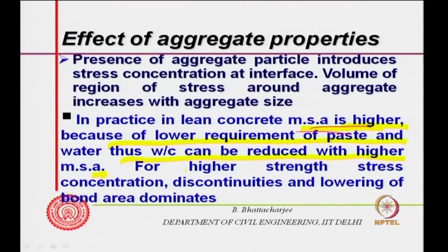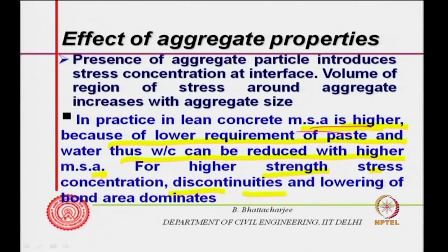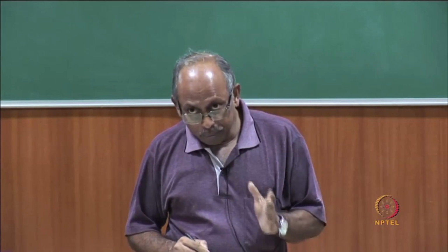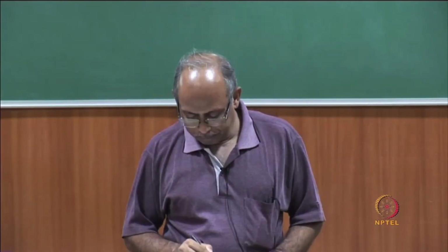You can have a low water cement ratio but higher MSA, but the paste should be less. For higher strength, stress concentration, discontinuities and lowering of bond area dominate, and therefore your MSA is limited to a certain value, something like 20 or 40 for structural, as I mentioned.